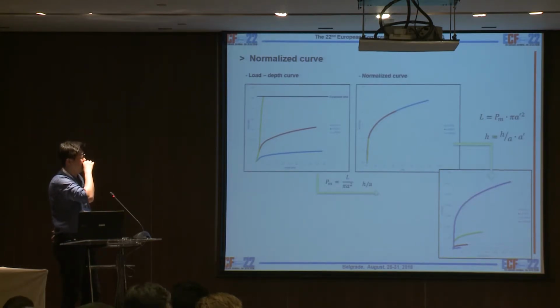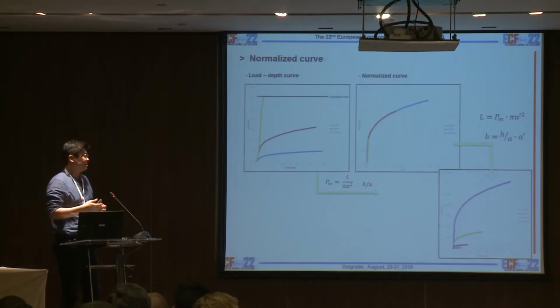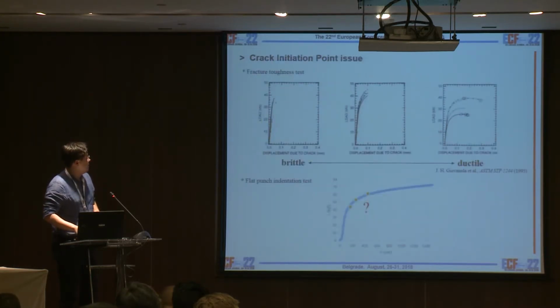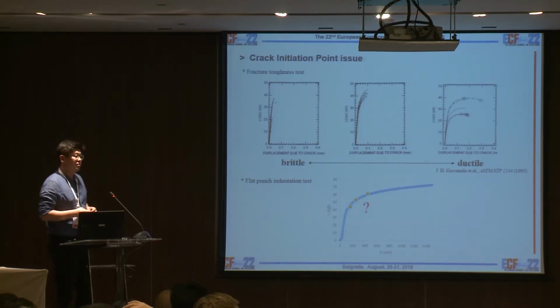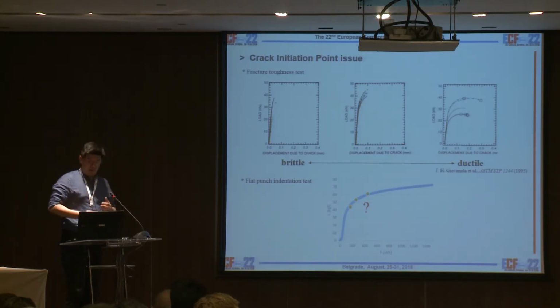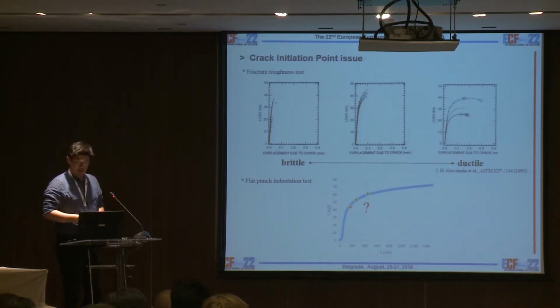And then finally, if we set another indenter size, meaning a virtual indenter size a prime, then we can convert to the indentation curve with a prime. So from this calculation, we don't have to test several different sizes of indenter. But still, we don't know the correct initiation point in indentation. There were no pop-ins, even if we used a larger indenter size.